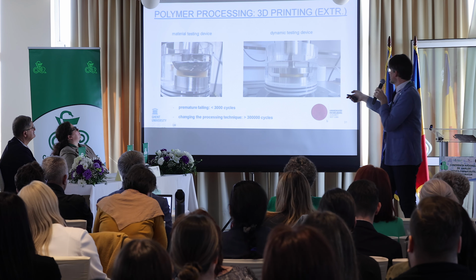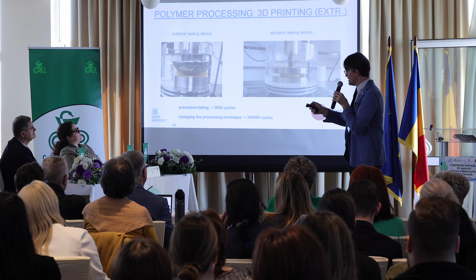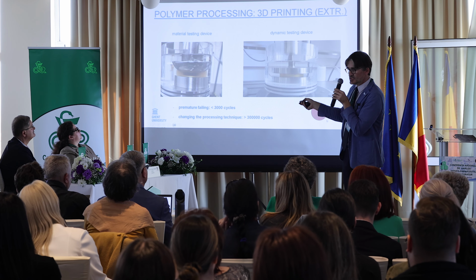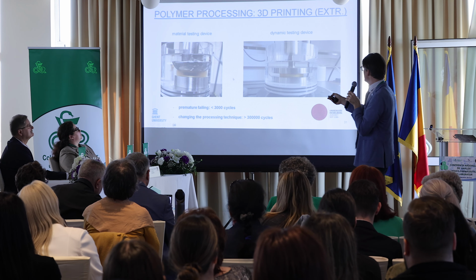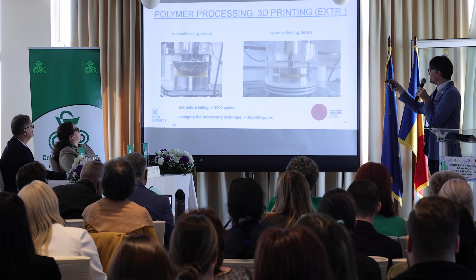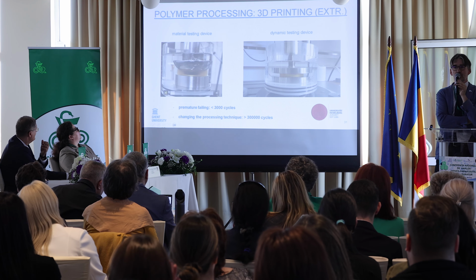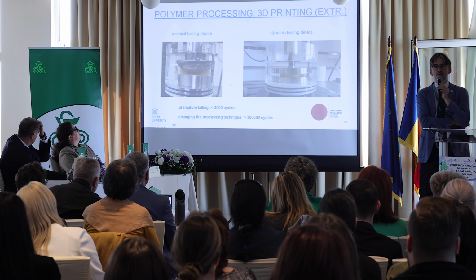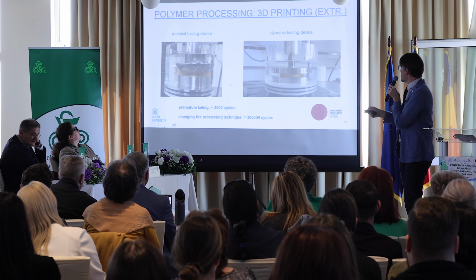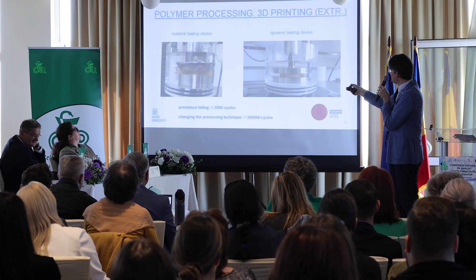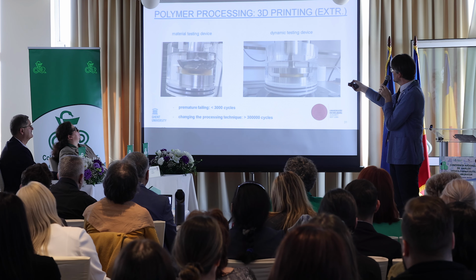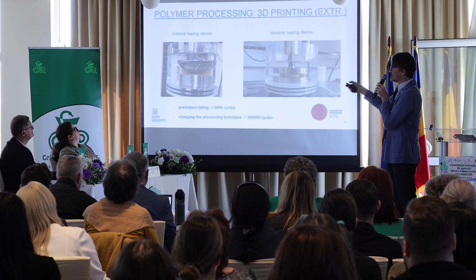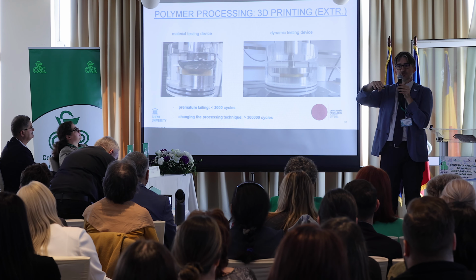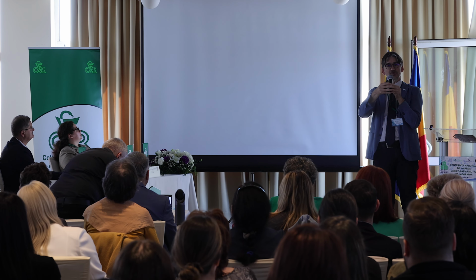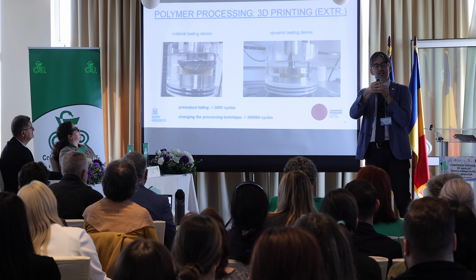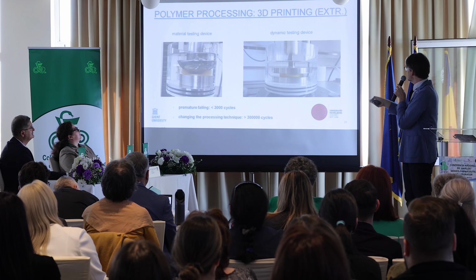These are two movies. I think if it would be possible, can I do that via the, or perhaps if you activate it there, I will give a short explanation already. This was for us the final proof whether or not the first generation materials could make it to an orthopedic application. What you see here on the left is a test of a hydrogel material under a so-called material testing device. You compress the material, you release the force, which means that the water can have the time to actually again be transported through the scaffold.